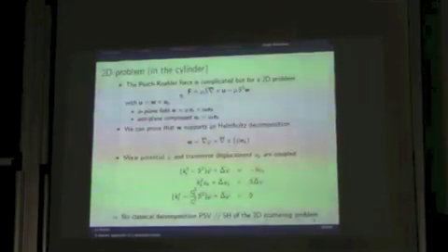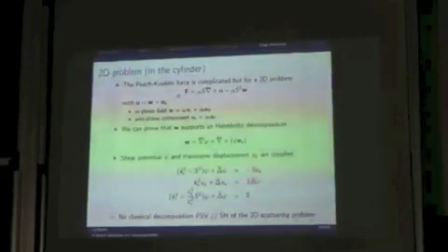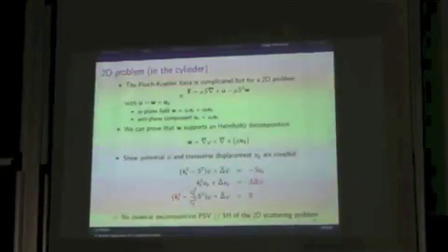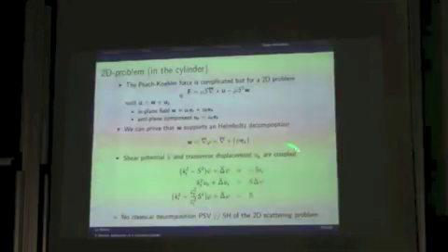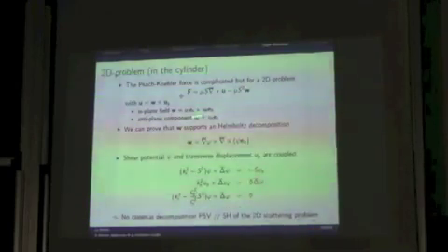So I will solve this problem in a very simple situation where I have a plane wave propagation in the 2-3 plane perpendicular to the Burger vector. In this case, we can show that the Peach-Koehler force is very simple, with a term related to the curl of the displacement, and another term which is related only to the in-plane field.